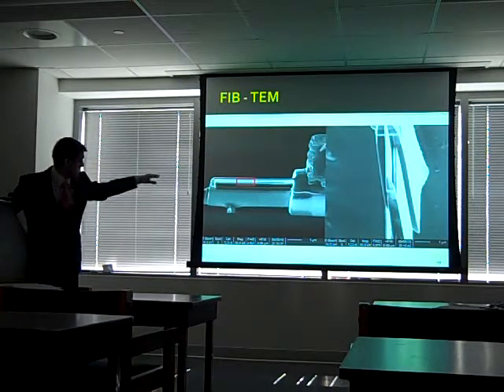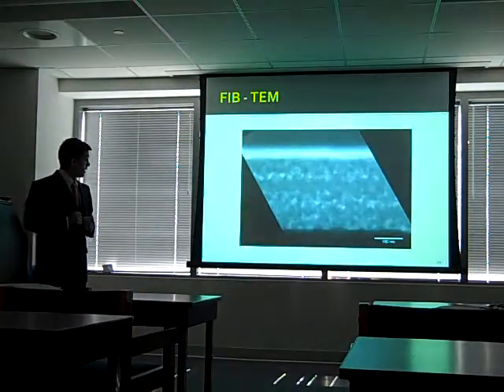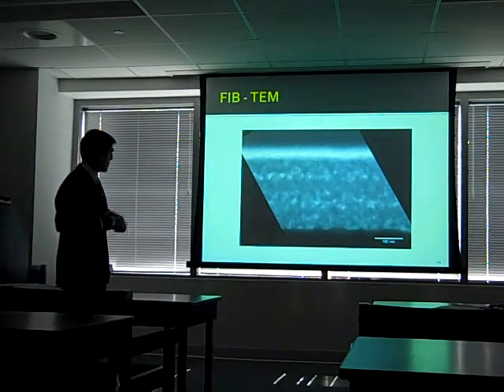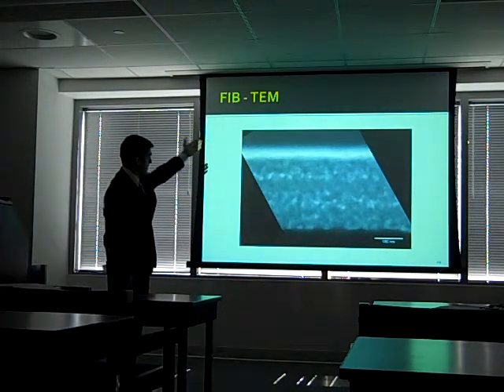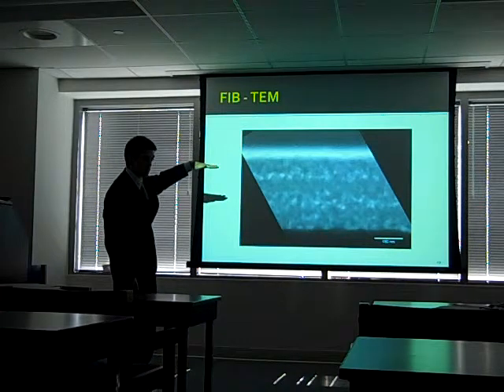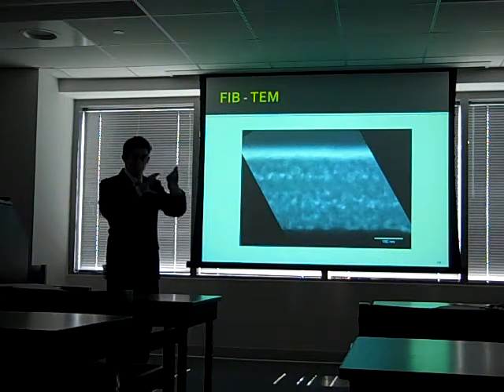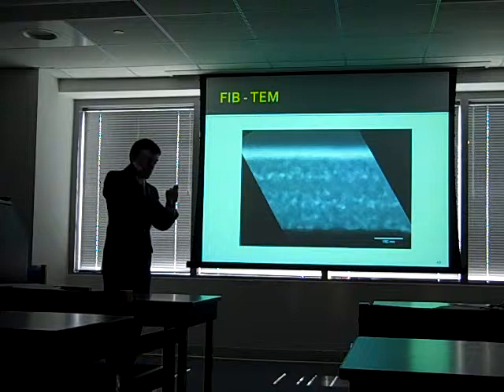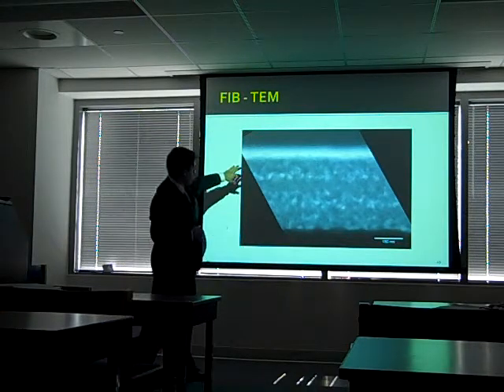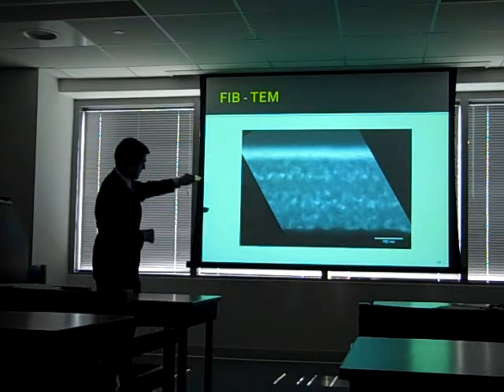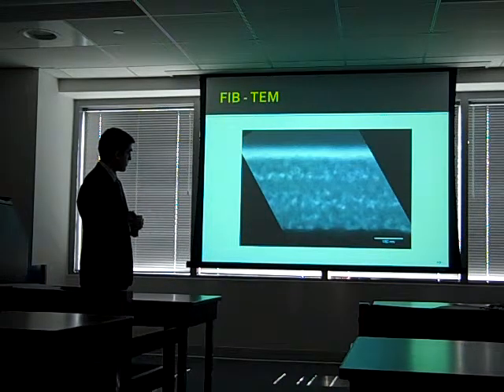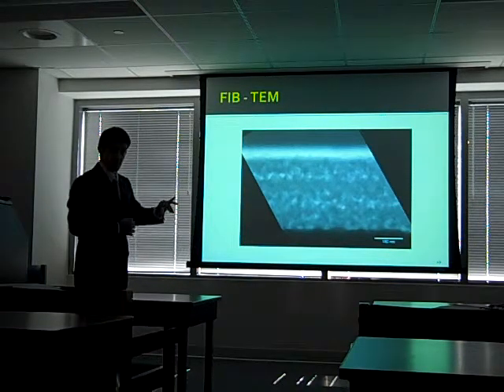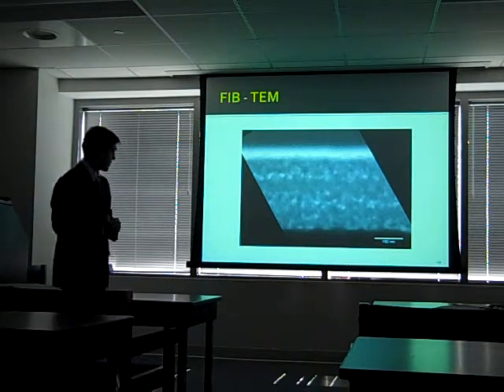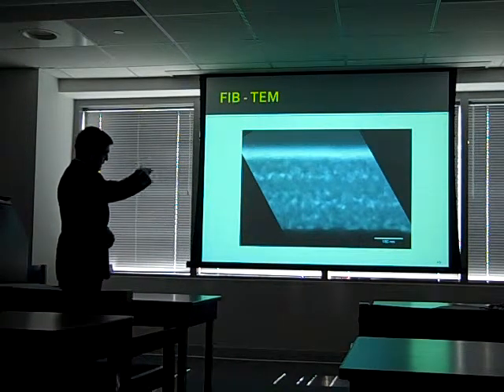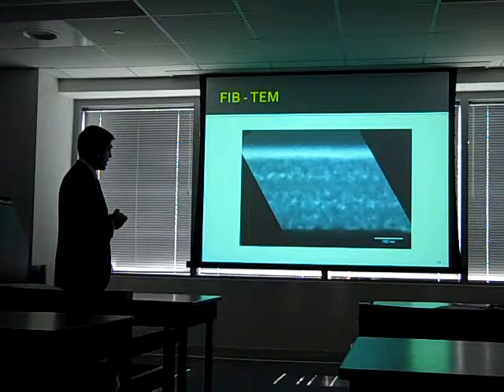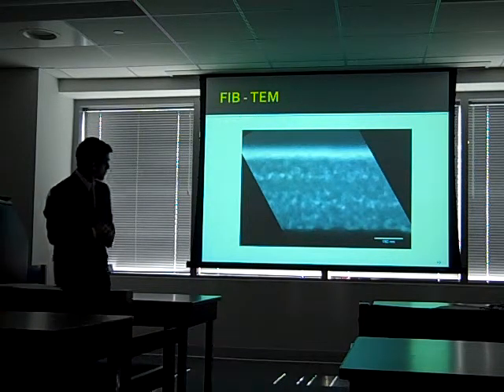So then we zoomed in on this red box here with the TEM, and this is what we found. So I'll explain the layers. From the top is a low-density platinum layer on top of carbon, which will just serve as protection for the ion milling. And then the film starts. So you can see 3 distinct layers of different compositions of BST. And then the black at the bottom is platinum. Okay, so also notice that the interfaces seem to be pretty rough, and there's white spots in there too.